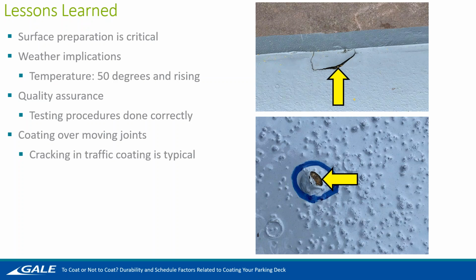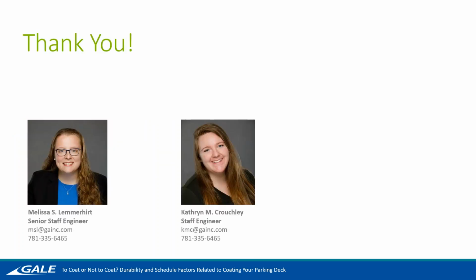And then coating over moving joints. As I said, we don't typically like to coat over precast parking garage joints or joints that will see movement. It will create cracking in the traffic coating if it's done over the joints. So the way we have come to combat that is we either terminate the traffic coating right before the joint, or you pull up your joint sealant and you coat actually into the joint and then put your sealant on top of it. So with that, that is to coat or not to coat. Thank you.